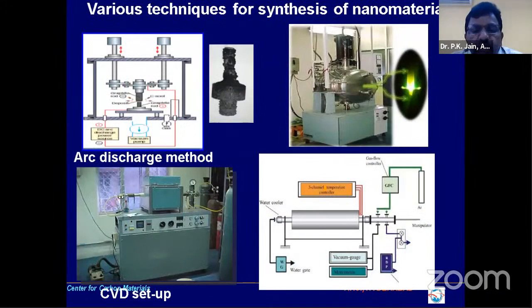Now the nanotubes can be synthesized by two or three techniques. Many techniques are there. What we have in our center is the arc discharge. The top one is the arc discharge. This is a closed reactor we filled, and the two graphite electrodes are there. After passing a very high current and voltage, one electrode will evaporate and deposit onto the other electrode, and this electrode will have plenty of carbon nanotubes.